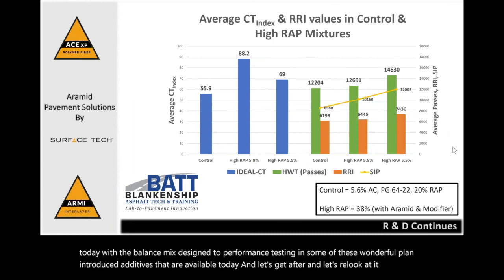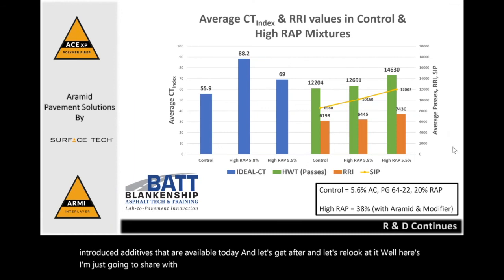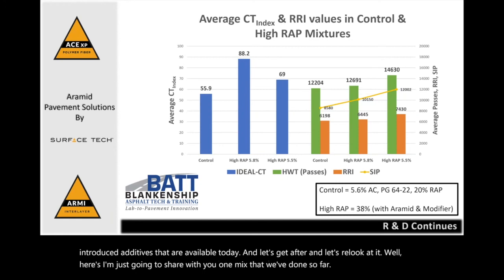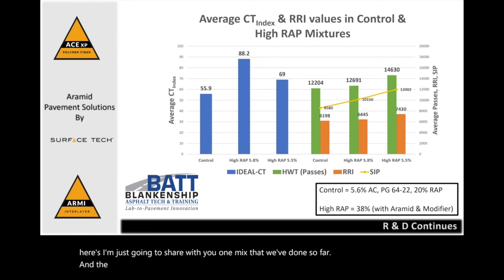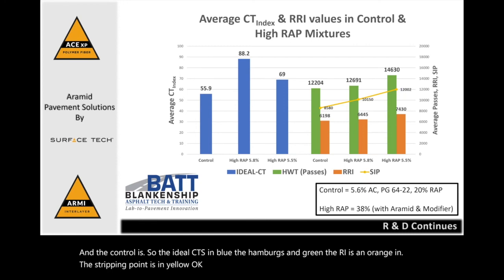I'm just going to share with you one mix that we've done so far. And the control, the IDEAL-CTs in blue, the Hamburgs in green, the RRI is in orange, and the stripping point is in yellow. Okay, but let's look at the control itself. It's 5.6% liquid AC, a 64-22, 20% RAP. Came back without any ACE in it, came back at 55.9.